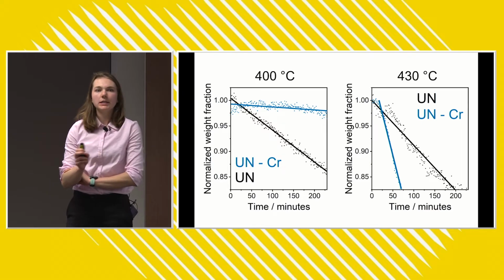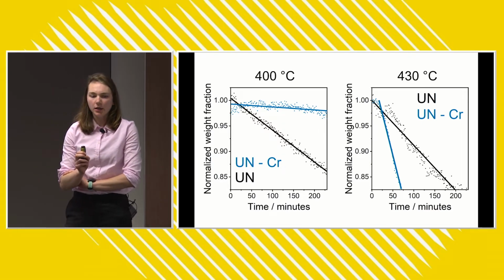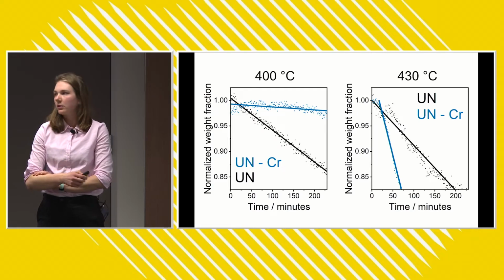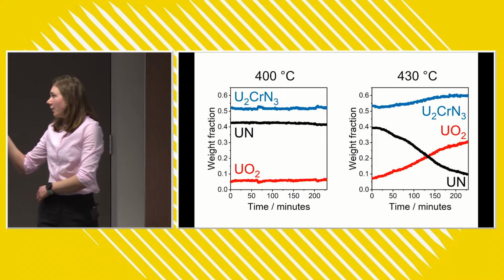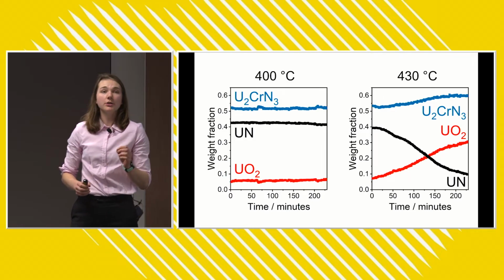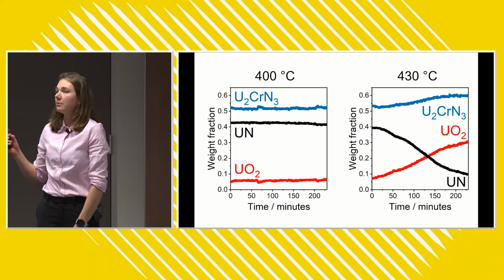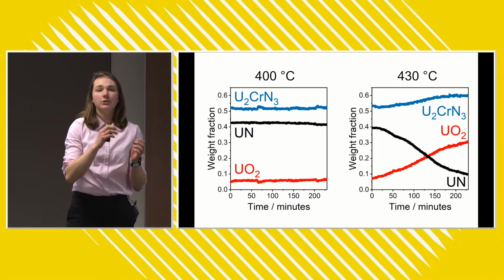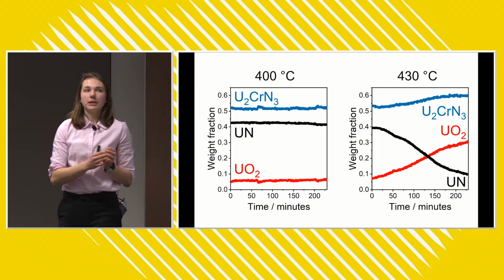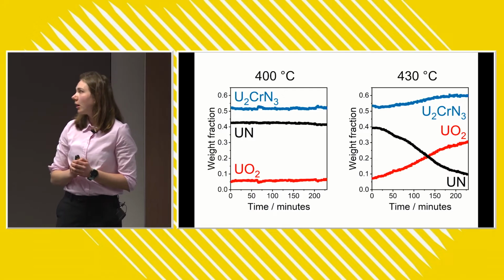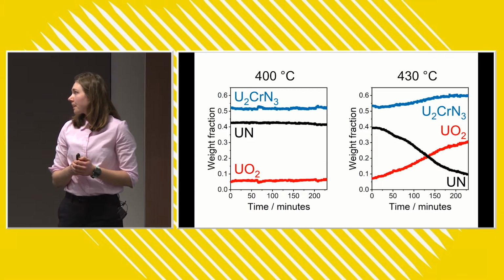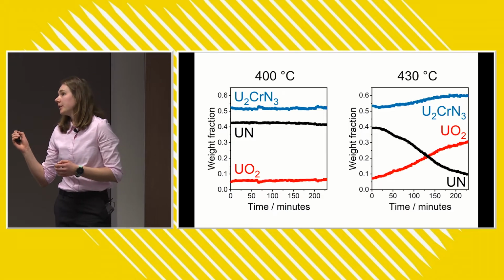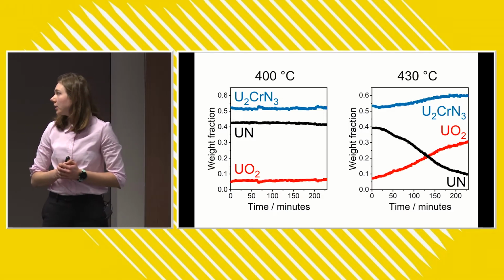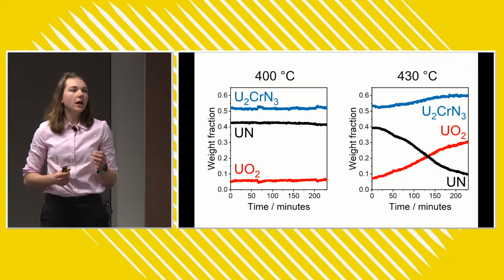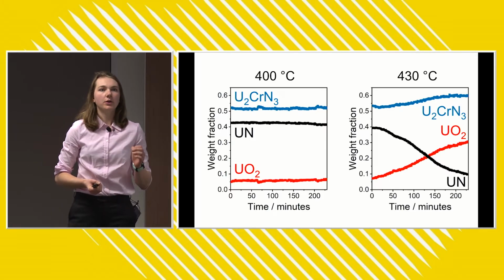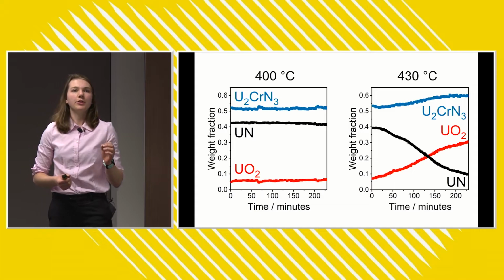And so using this in situ technique, we can actually figure out why. By identifying the materials that are in that fuel pellet, we can see that the chromium isn't actually going directly into the uranium nitride. It's forming this secondary phase that you can see in blue there at the top, the uranium chromium nitride. And so if we look at the 430 degree plot there, it's the uranium nitride component that is being preferentially oxidized over the material that contains that chromium.